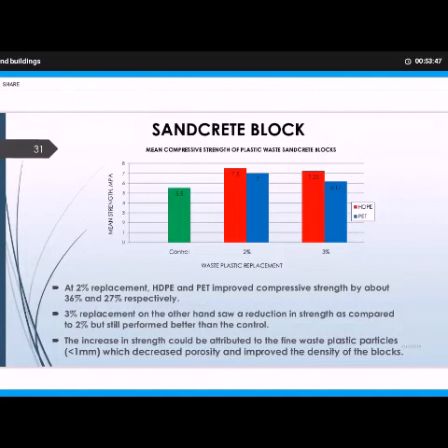And if you can see from the graph, the control, that is the material without the plastic waste, is obtaining strength around 5.5. Now the standard for blocks says that you should not get anything below 2.8 megapascal. So the control is having 5.5 megapascal, which is very good, way beyond the minimum standard. But if you add 2%, you realize that the strength increases. For PET, it increased to 7, and for HDPE, it increased to 7.5. And when you add 3% of the same plastic waste, for HDPE we are seeing 7.22, and for PET we are seeing 6.17, which is very good. They are all going beyond the control.